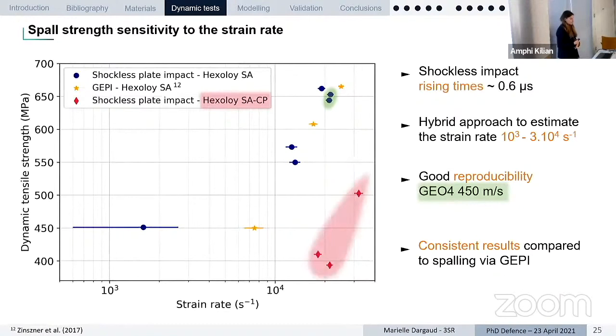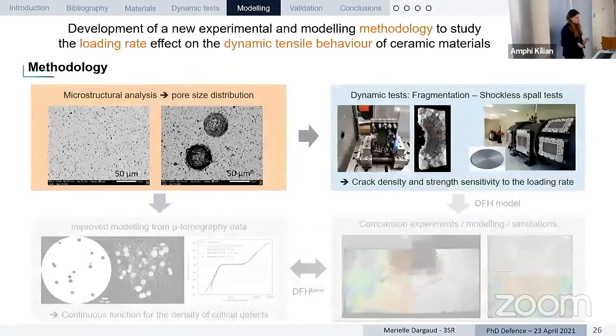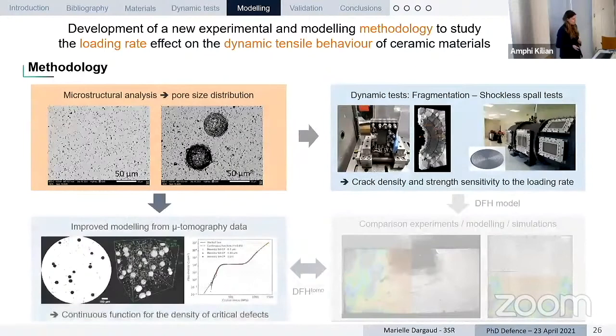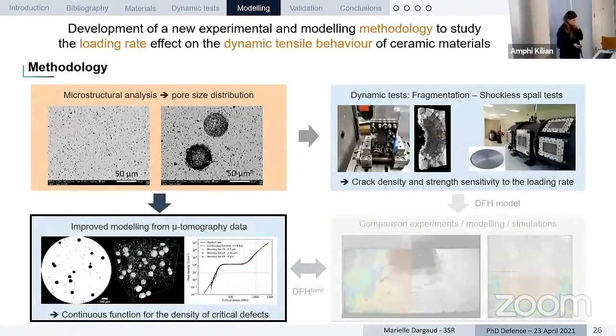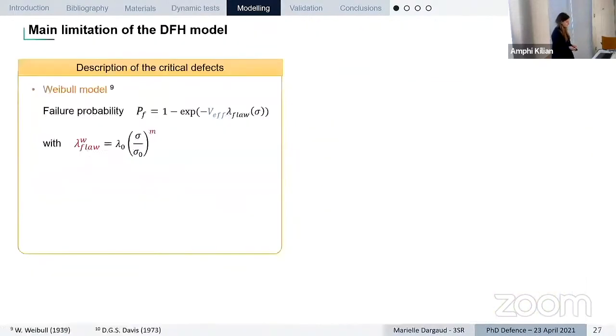We've done some additional tests on the Hexoloy SA-CP, and we can see here that the dynamic tensile strength is slightly lower than the first material, but still we have this sensitivity to the strain rate. So now that we have experimental data, in parallel, we're working on a modeling work to be able to predict the behavior of the material.